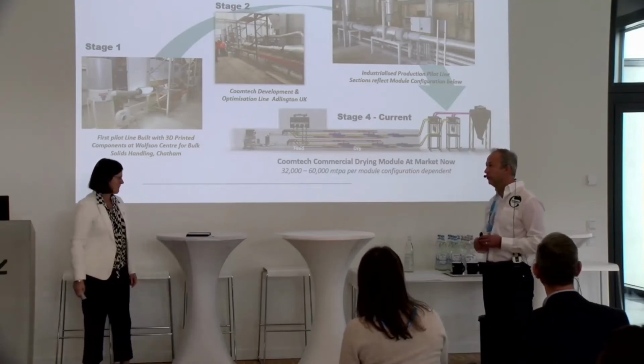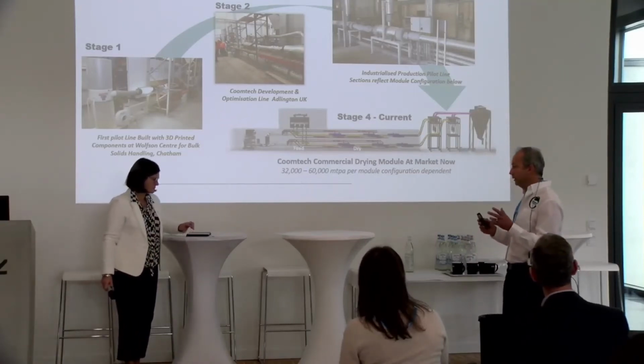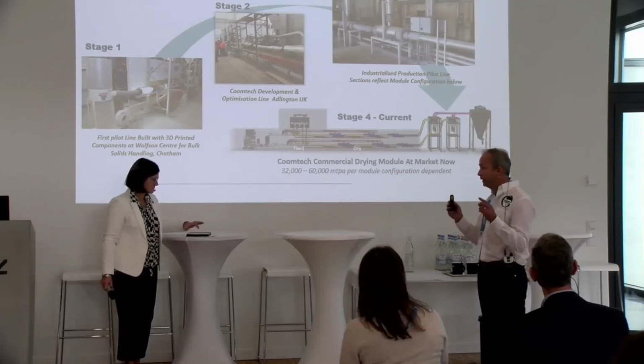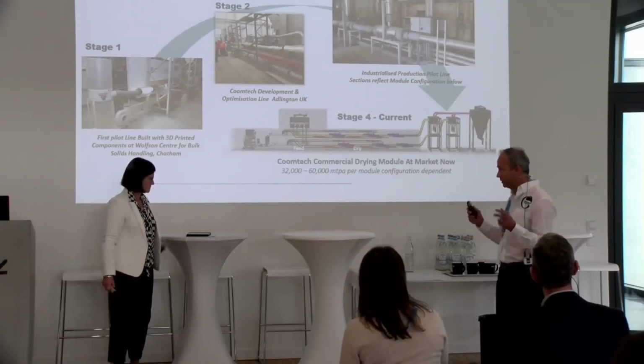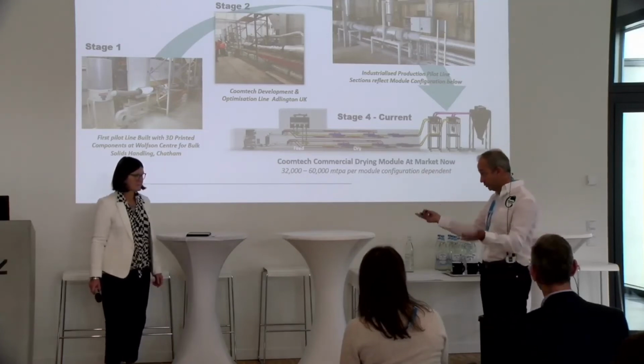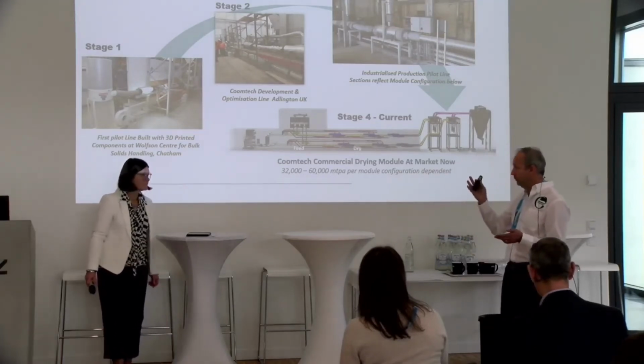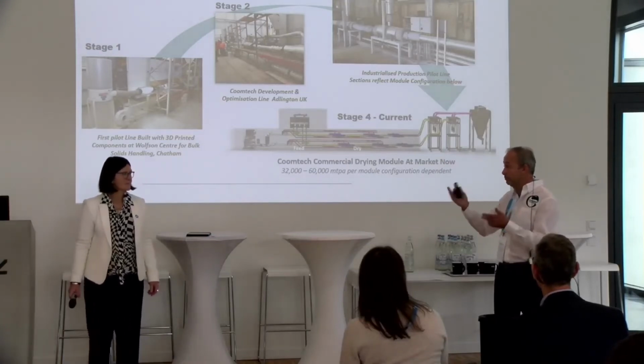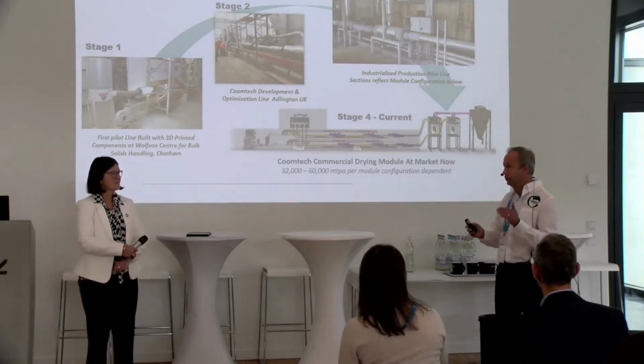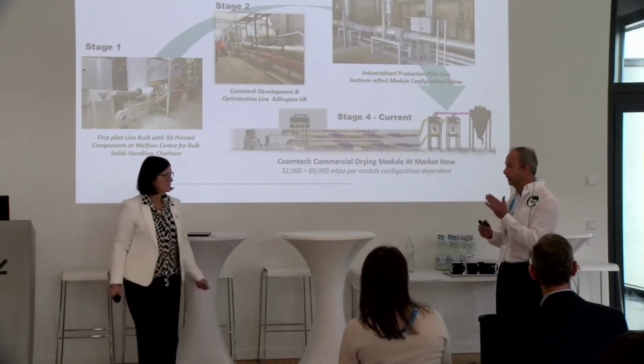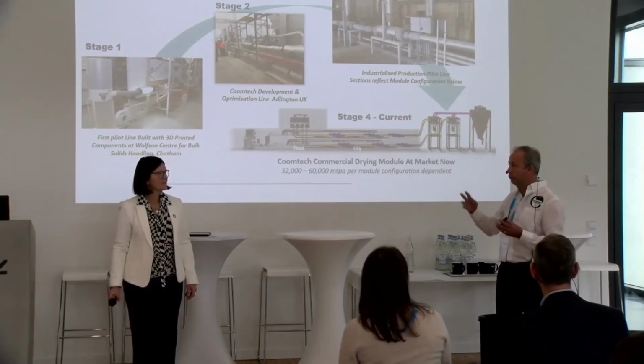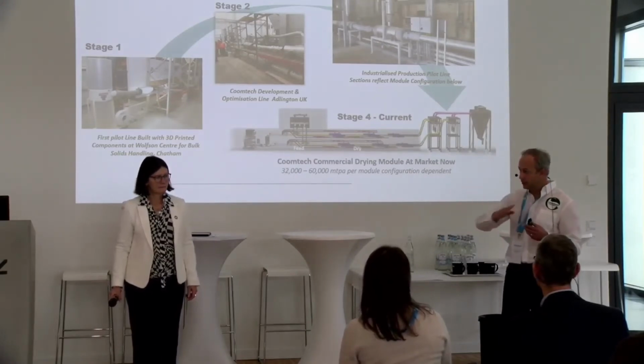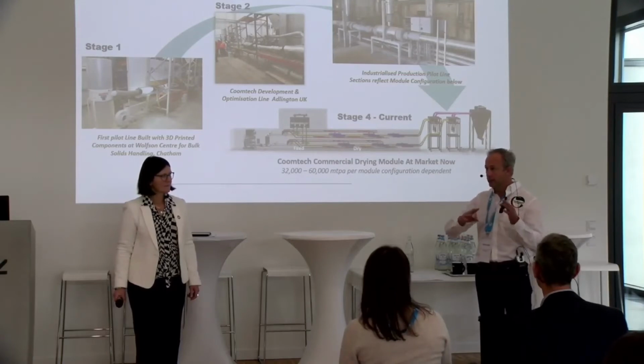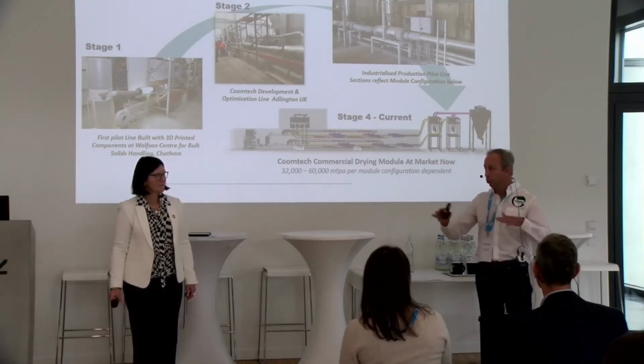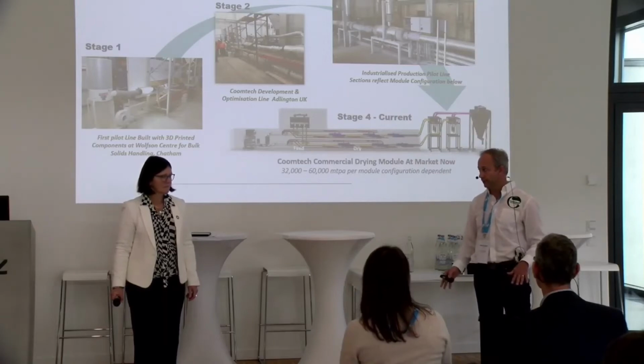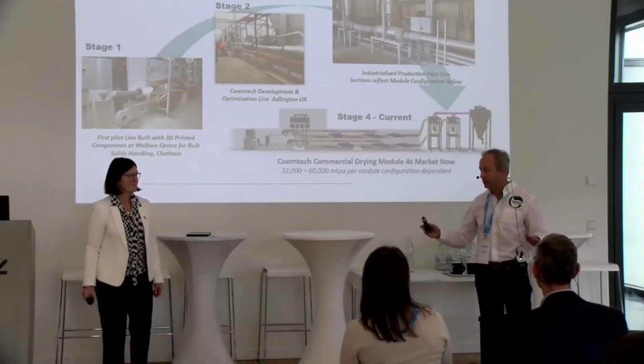It's a good question. If you look at, I think the correct term is a psychrometric graph of the moisture carrying capacity of air versus temperature, which is what somebody in that situation would need to do, it's an asymptotic graph. So basically, you solve that problem if it arises. It depends specifically on what the moisture level is. You solve that problem by increasing slightly the temperature of the transport air. Having sheared the moisture off the material, we need to keep the transport air at a sufficiently warm temperature that the water does not recondense. So that's all we have to do. It's much lower temperature than boiling it off.